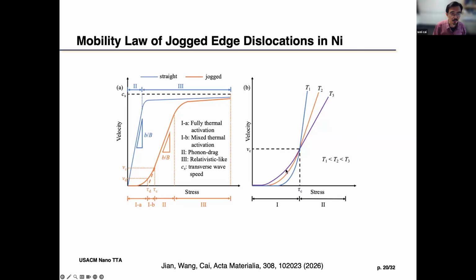And this is what we find if you increase the temperature, only the temperature. This is a very surprising finding: as you increase the temperature, all of these velocity-stress curves seem to pass through an invariant point. And this was never reported before. It's very nice, in that if your stress is below the critical stress, you're in a thermally activated regime where, if you increase temperature, it will increase the velocity.